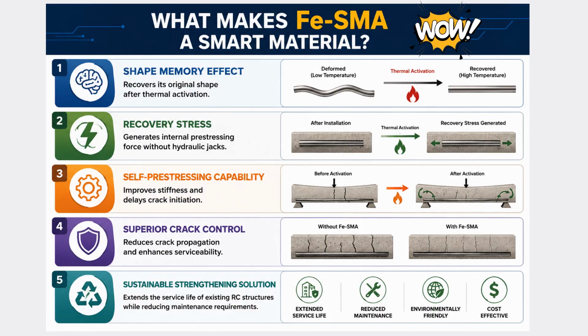What makes Fe-SMA a smart material? After thermal activation, it generates recovery stress that creates internal pre-stressing without hydraulic jacks. This improves beam stiffness, delays crack formation and crack propagation, and extends the service life of RC structures.